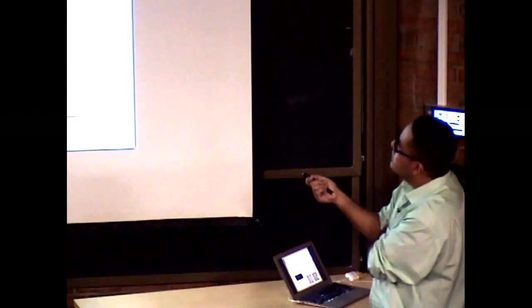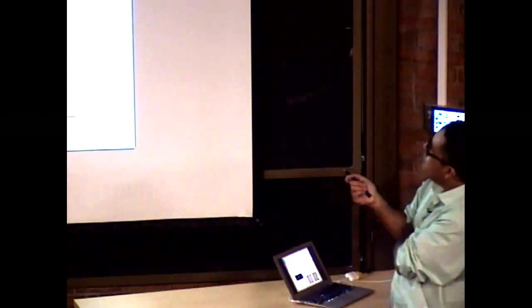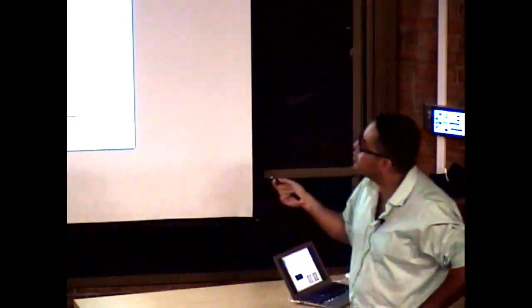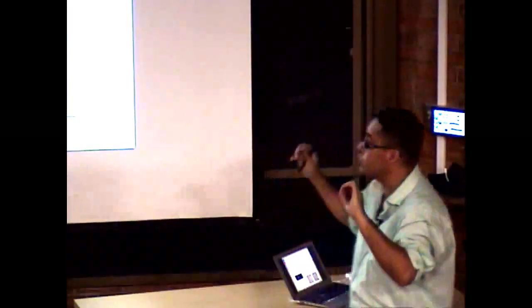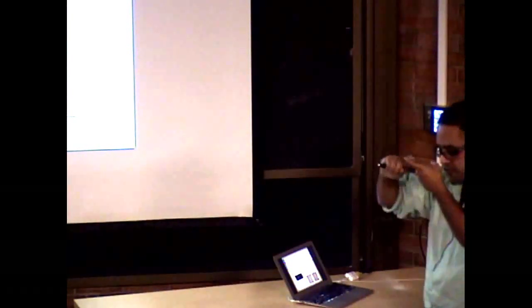But then there was this very intriguing paper from John Lupton. I think here, yes, he's still listing the University of Utah in this paper. This is a paper that came out in 2013, I believe, with really very clean measurements of single chain emission spectra. So here is the same material, P3HT. I think the molecular weight that they were using was right in the middle between these two different regimes that I talked about, of very polycrystalline versus two-phase microstructure. So they're right in between in terms of molecular weight. That will be important in how the chain coils, how it can coil, and so on.